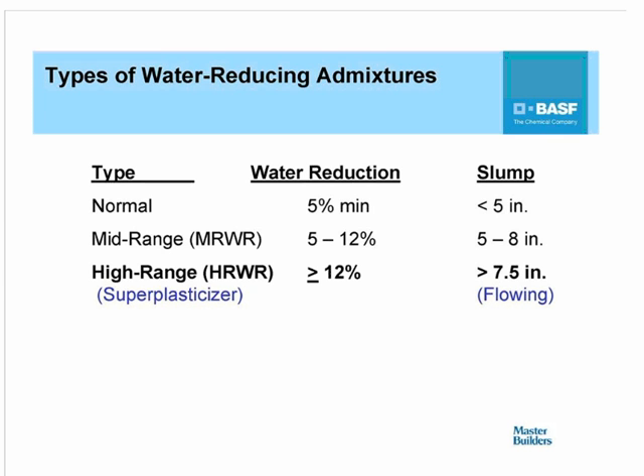Now, the last category under water-reducing admixtures will be the high-range water-reducing admixtures, or as they're more commonly known within the industry, superplasticizers. And these admixtures, by specification, have to provide a minimum water reduction of 12% when used in a concrete mixture. Most of them actually provide water reductions much greater than that, and in the extreme cases, we can get as much as 40% reduction in total mixed water content. The main benefit of high-range water-reducing admixtures is that they're used in producing flowing concrete. So these are concretes that have slumps of 7.5 inches or greater.